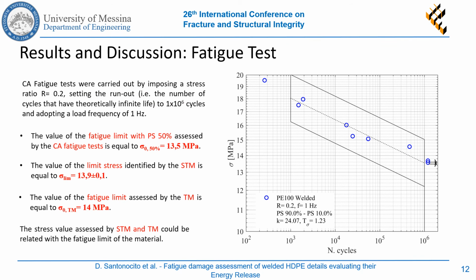A series of fatigue tests has been carried out on 9 specimens with constant stress amplitude from 13 up to 19 MPa, and the same stress ratio and frequency of the stepwise fatigue test. The test results are reported in an S-N plot adopting a number of cycles run-out of 1 million, with a scatter band for a probability of survival of 90 and 10%. The fatigue limit estimated with a probability of survival of 50% is equal to 13.5 MPa.